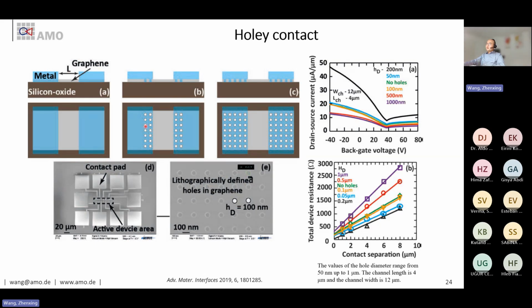Another approach is what we call holey contact. So we try to make a lot of holes in the graphene, basically to increase the edge where you can inject the carriers. With that, we can really also achieve very nice contact resistance. So this is also what we have done several years ago.